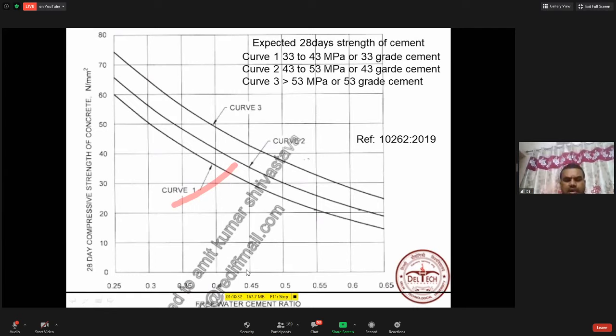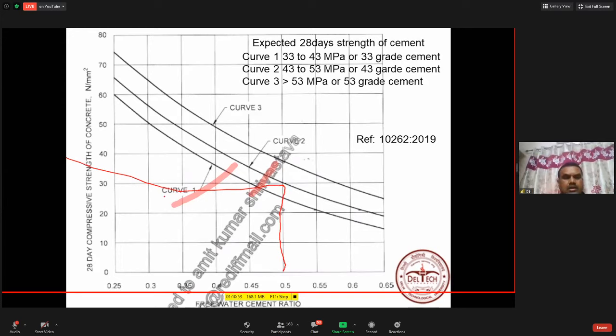So now you see, for a given water cement ratio, you will get a given 28 days compressive strength. Now, if I say our water cement ratio is 0.5, and if I am using 33 grade cement, then I will get M30 grade of the concrete. You see, if it is 0.5, then I will get 30 grade of the concrete here. You see, 30 grade of the concrete here.